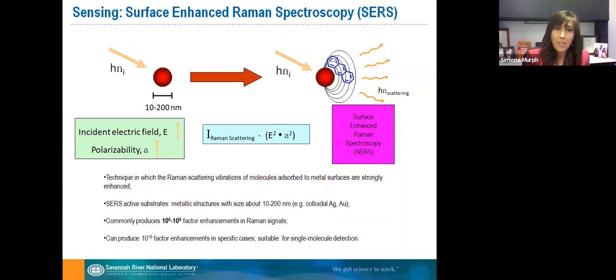So of course, for sensing applications, if you shine the light on these nanoparticles and you place an analyte of interest in close proximity of the nanoparticle, you can get an enhancement response. Why is that? Because you actually couple the plasmon band of the nanoparticles with the resonances of your analyte, and you can get enhancement effects. So the intensity of the Raman scattering is directly proportional with the incident electric field and the polarizability of your molecule. And here usually the best nanoparticle substrates are gold and silver, because you can actually couple the plasmon band of the nanoparticles with the laser line.